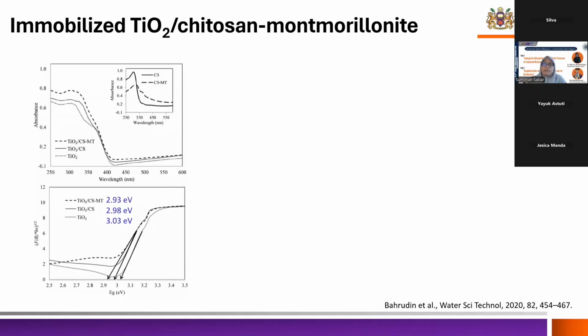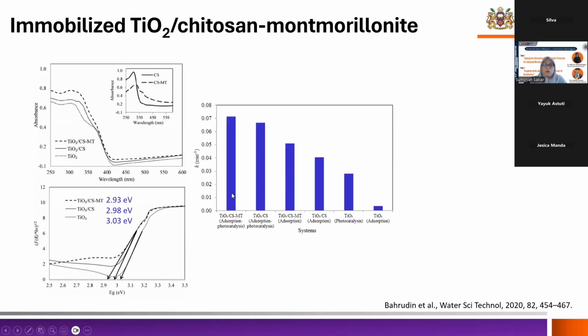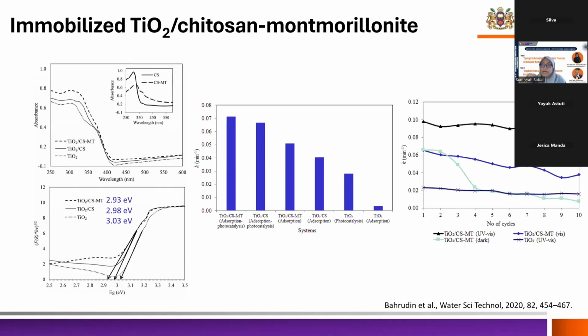by combining it with montmorillonite. Okay, so we observed that when we modify the chitosan, it has improved the visible light activity of the photocatalyst. And it can be seen that once we add the montmorillonite into the chitosan, the band gap energy has decreased from 3.03 to 2.93 electron volts. So we also observe that there is an increase in the adsorption properties of the photocatalyst that in the end improves the overall photocatalytic activity. And furthermore, the photocatalyst is also reusable. It can be reused up to 10 cycles without any significant decrease in the photocatalytic activity for methyl orange.